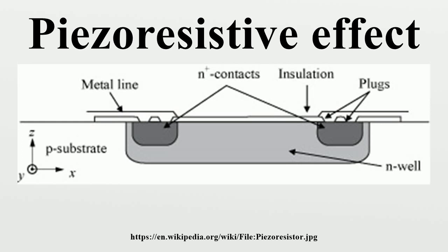The piezo-resistors: Piezo-resistors are resistors made from a piezo-resistive material and are usually used for measurement of mechanical stress. They are the simplest form of piezo-resistive devices. Piezo-resistors can be fabricated using a wide variety of piezo-resistive materials. The simplest form of piezo-resistive silicon sensors are diffused resistors, consisting of a simple two-contact diffused N or P wells within a P or N substrate. As the typical square resistances of these devices are in the range of several hundred ohms, additional P-plus or N-plus diffusions are necessary to facilitate ohmic contacts to the device.